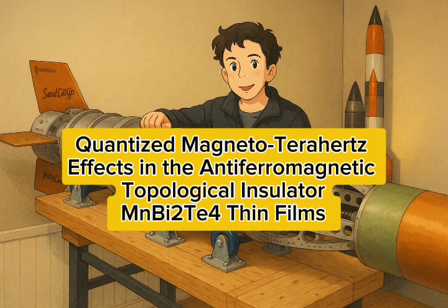How do they separate the transmitted signal from the reflected one if it's all happening fast? That's the time-domain part. The initial pulse goes straight through, that gives the Faraday rotation, but some light reflects inside the substrate and comes out a bit later. This first echo pulse contains information about the Kerr rotation from the MBT-substrate interface. Clever. Using the timing of the echoes, like sonar, almost. Kind of, yeah. It lets them disentangle the different signals. And their terahertz source covered the 0.4 to 1.6 terahertz range, which, as you said, matches the expected energy gap size.